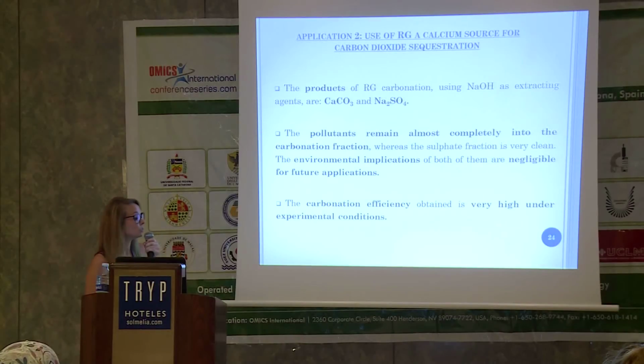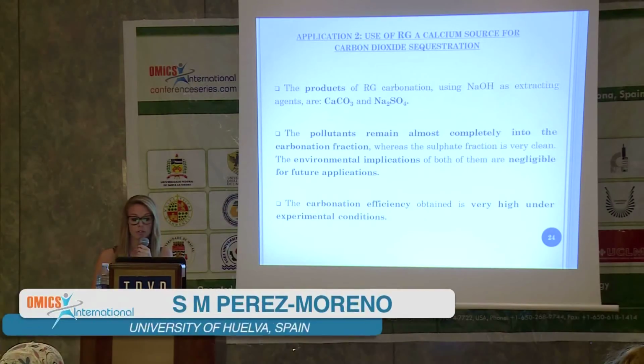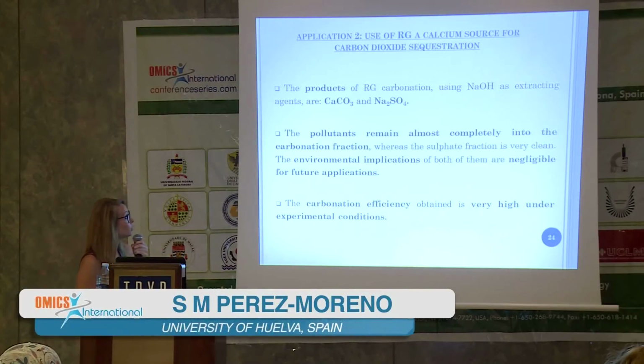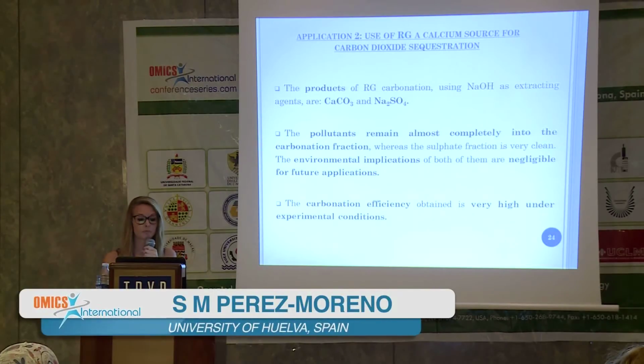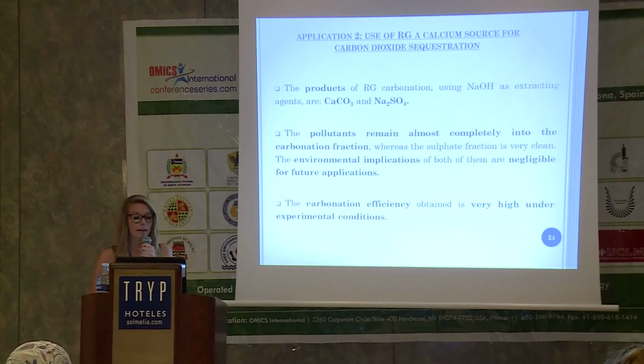In the second application, where red gypsum is used as a calcium source for carbon dioxide sequestration, the product of carbonation using a solution of sodium hydroxide is mainly calcium carbonate and sodium sulfate. The pollutants remain almost completely in the carbonation fraction, whereas the sulfate fraction is very clean. The environmental implications of both are negligible for future application. And the carbon efficiency obtained is very high under experimental conditions.